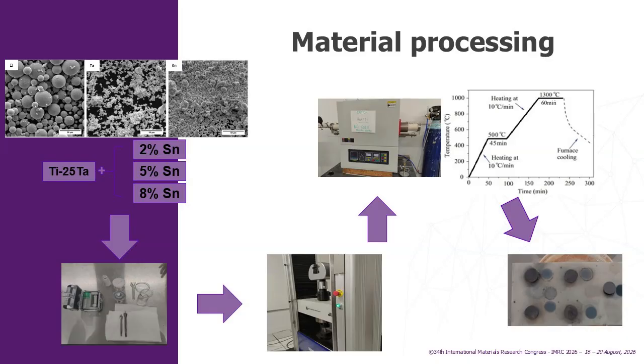The sintering process was carried out following isothermal ramps. First, the samples were heated at a rate of 10 degrees per minute up to 500 degrees for 45 minutes. Then, the samples were heated to 1300 degrees, where they were maintained for 60 minutes. And finally, the furnace was cooled slowly to extract the samples.